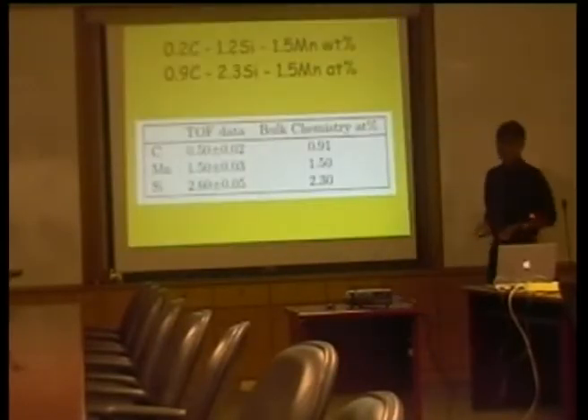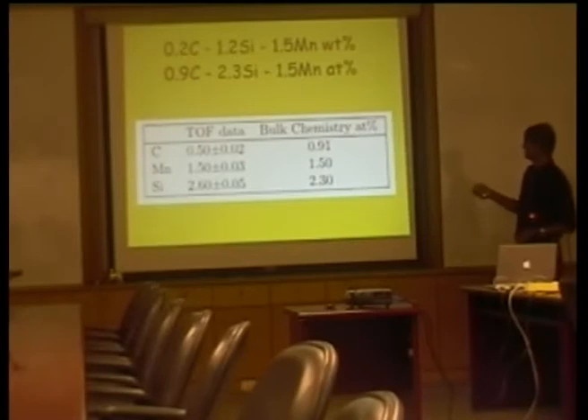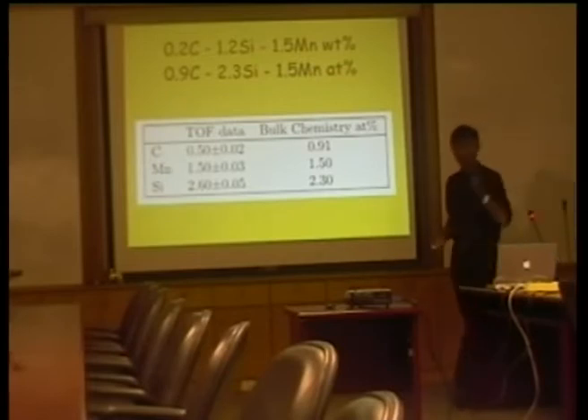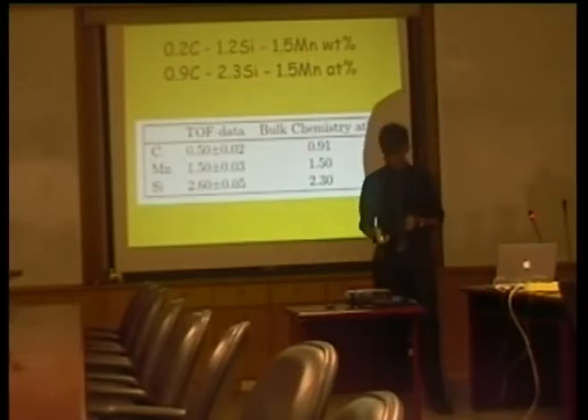So just to summarize, this is the starting composition in atomic percent. And this is what we find experimentally, that the ferrite has gained quite a lot of carbon from almost zero, which we expect at equilibrium. The manganese and silicon are more or less the same as the starting manganese and silicon concentration.